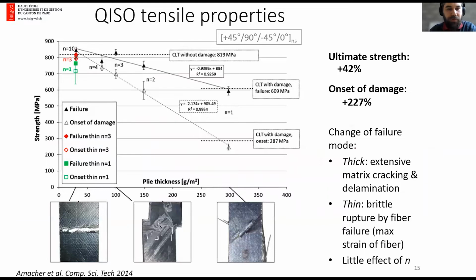If we report these different test results for different ply thicknesses, these are quasi-isotropic laminate tensile tests. We have here in dashed line the onset of damage, so the onset of acoustic emission, and in continuous line the fracture, so the failure strength of the laminate. We can see that for the thick ply, the first onset of damage is very early, at about 1/2 of the strength of the laminate.